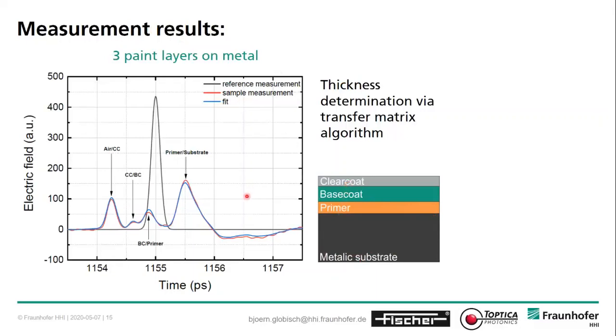And when you now look at the terahertz signal, which is now a processed signal, after going through all these algorithms and the transfer matrix model that we use for it, you get these nice results here. So you can clearly distinguish the primer from the substrate. You get the interface of the base coat and the primer. You get the clear coat and the base coat, and then you get the interface between air and clear coat. So you can nicely distinguish between all these layers. And from the time difference between these layers, you can calculate the thickness.